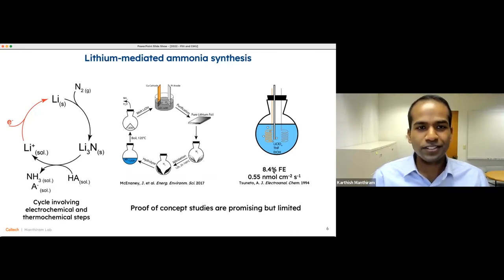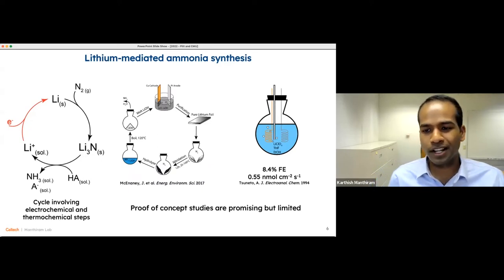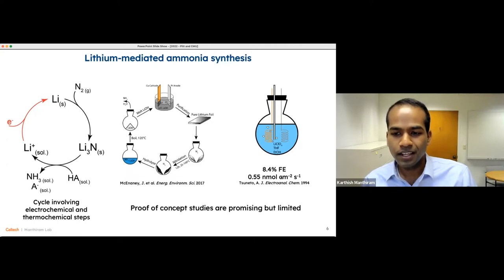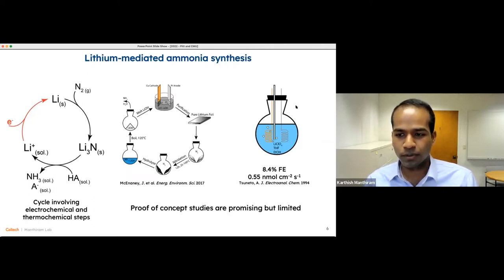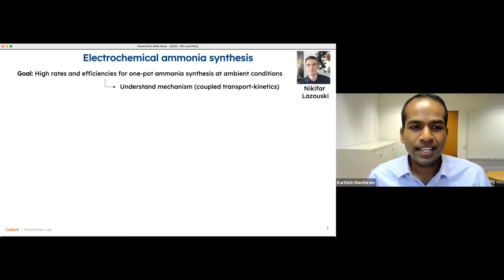So the Faradaic efficiency is defined as the fraction of electrons that go toward making the desired product. With a Faradaic efficiency of 10%, for instance, that would mean that 1 in 10 electrons are going toward making ammonia, while the rest go toward undesired products, here hydrogen. You'll see also that the rates are pretty modest, 0.55 nanomoles per centimeter squared per second. So there's a lot of room for improvement here when it came to this one-pot process for converting nitrogen into ammonia at ambient conditions.